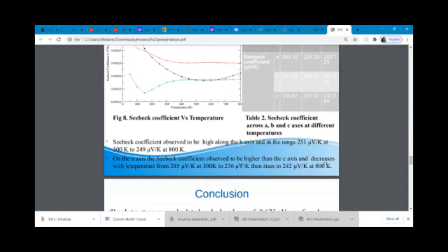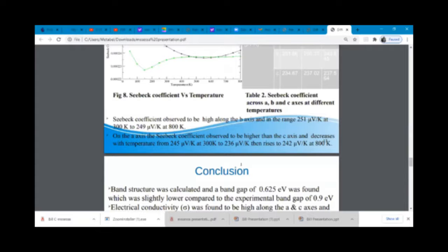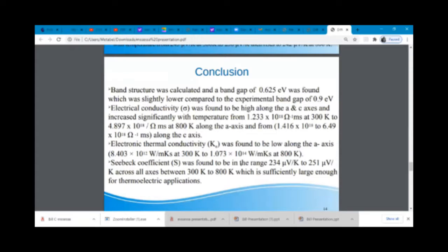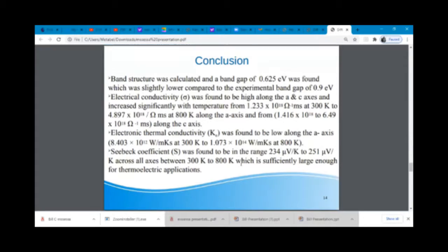So as I conclude, I can say that the calculation of these properties using first principle methods proved to be insightful. I was able to get the band structure, but it was slightly lower than the experimental value. This is understood as DFT tends to underestimate the band gap. Also, the electrical conductivity of the material was found to be increasing significantly with the temperature. I've given the range there, which is very good. Shows that the material is a very good conductor at high temperatures.